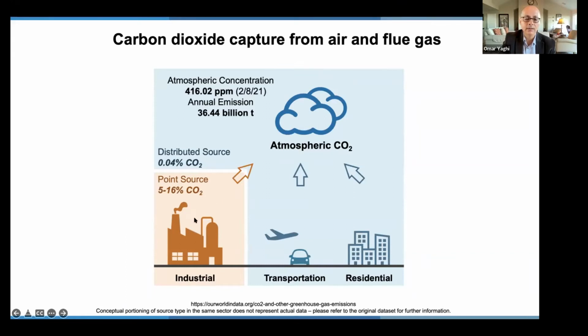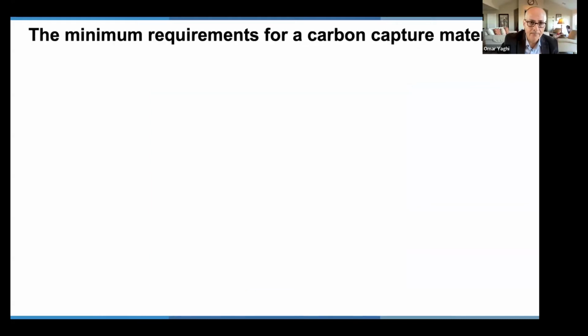The other challenge is to be able to capture the CO2 from point sources such as power plants. And there the concentration is much higher than in the air. It's 5 to 16% CO2, depending on whether you're burning natural gas or petroleum. So these two challenges, capturing CO2 from point sources and capturing CO2 from air, require slightly different functionalization of the MOF. So let me show you what we need to be able to do.